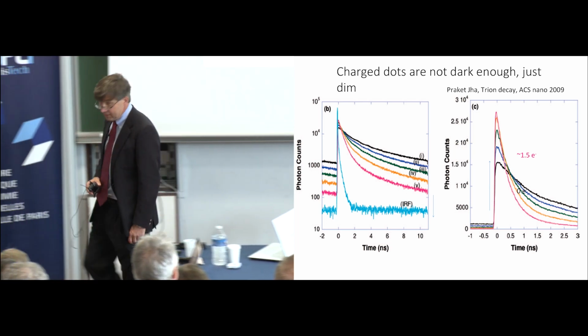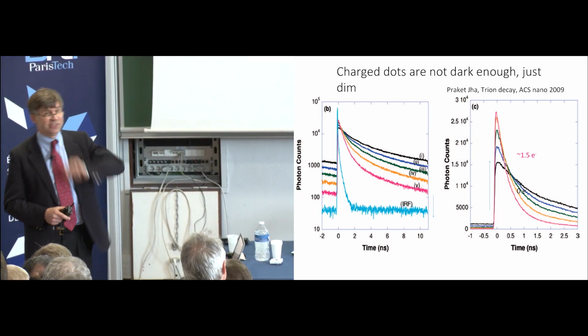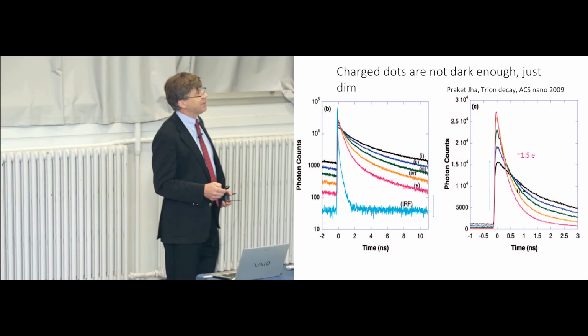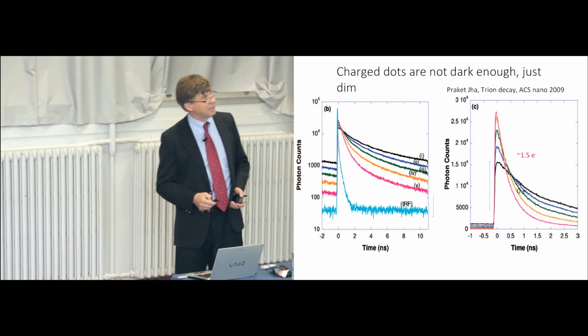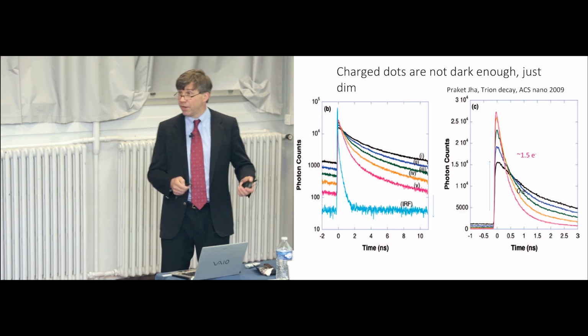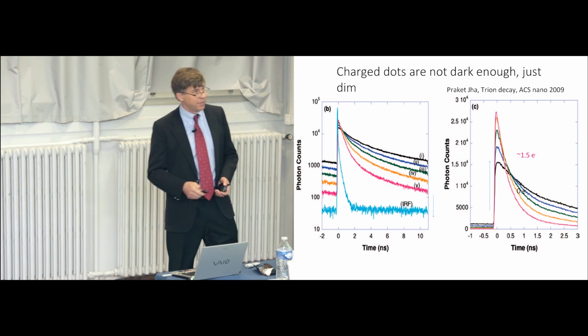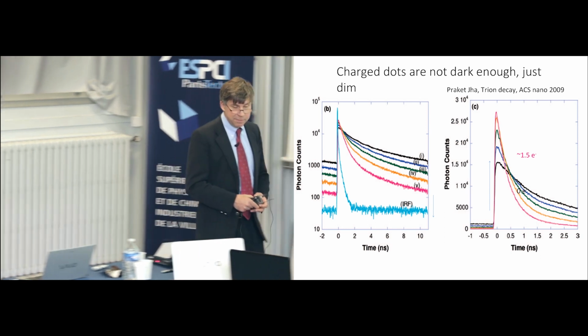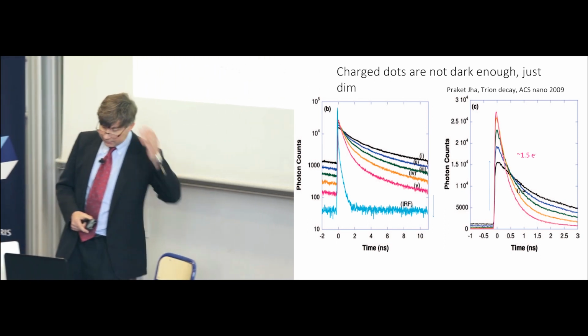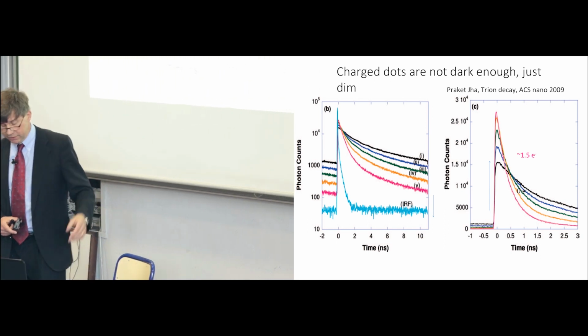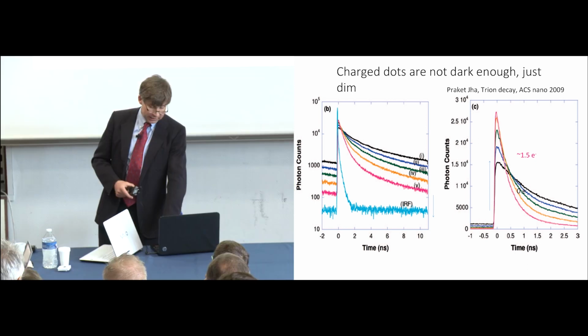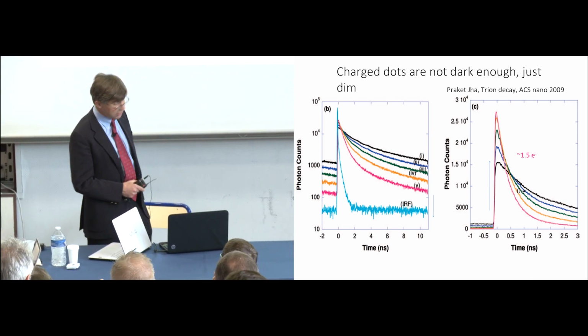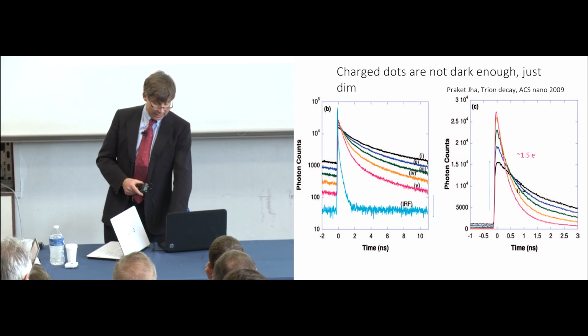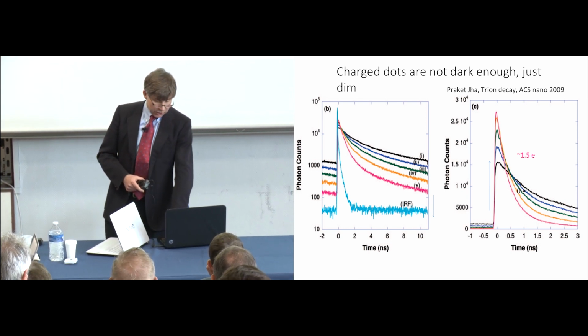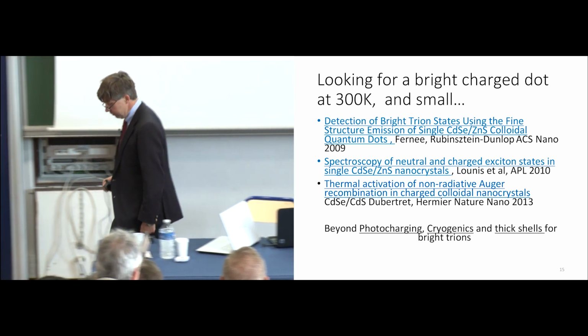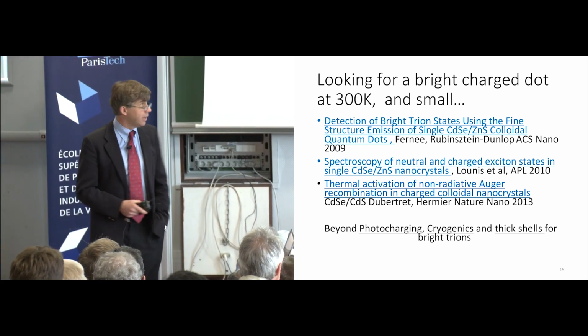Eventually, I think we at least could show that negative charged dots are not dark because we could measure their PL. We could see that, for example, a negative charged dot has brighter PL at early times, even though the integrated PL is weaker. And so we were able to finally, we certainly were convinced already, but we were able to convince others that the negative trion is not dark enough to be the dark state in blinking. So then we started looking for a bright negative trion.